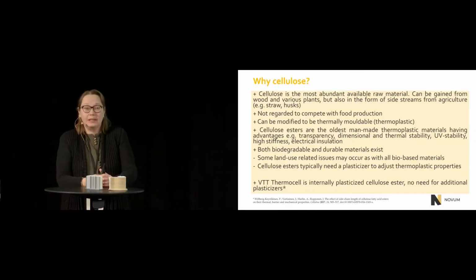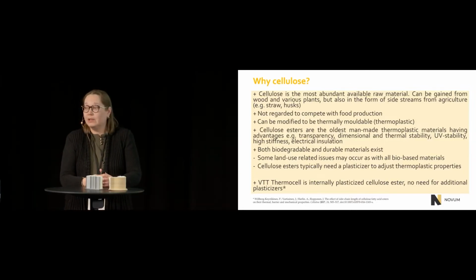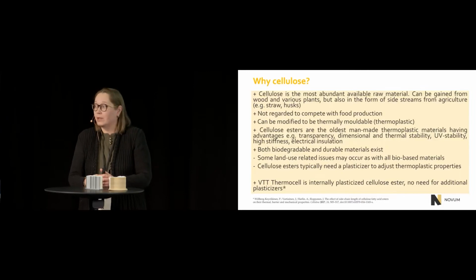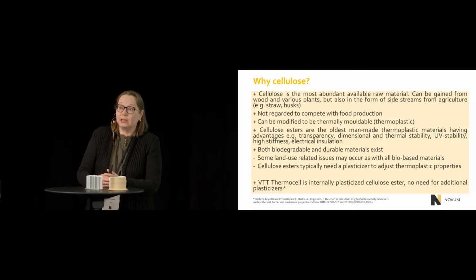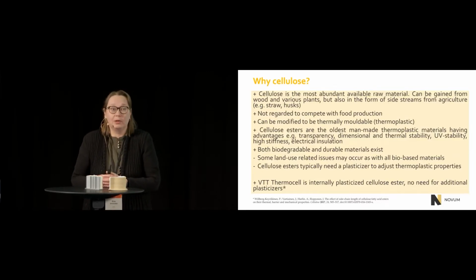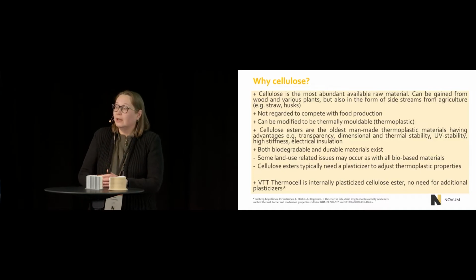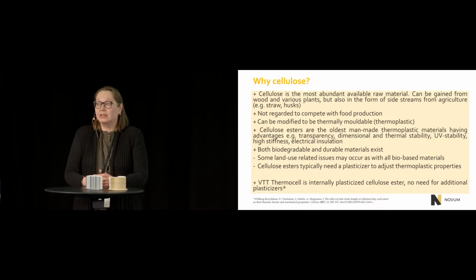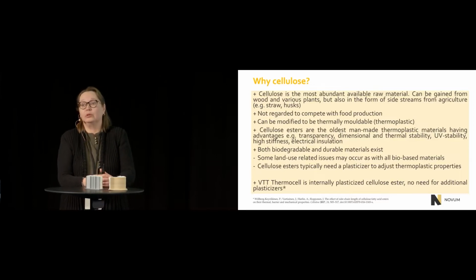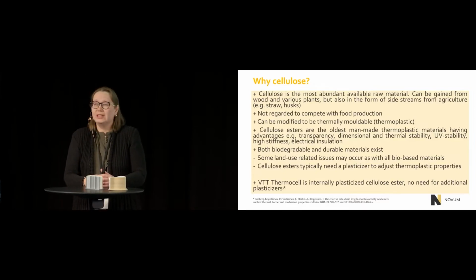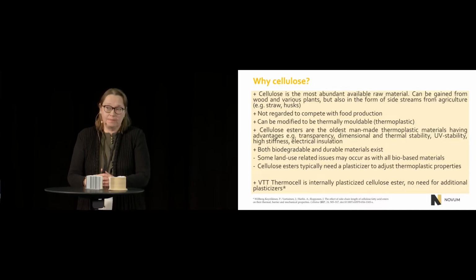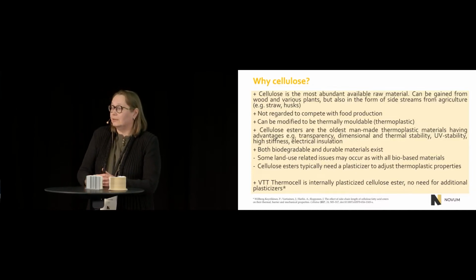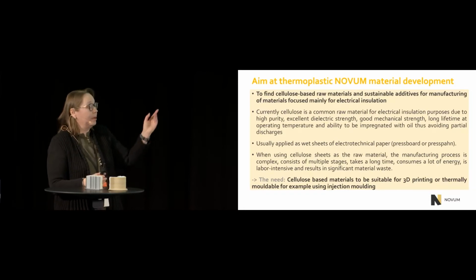If you think of these cellulose esters, they typically need a plasticizer to adjust the thermoplastic properties, which is a bit of a drawback. For that, VTT has developed a Thermocell material, which is an internally plasticized cellulose ester where the plasticizer is coupled to the cellulose backbone. So there is no need for additional plasticizer. You can read more about that, for example, in our publications.